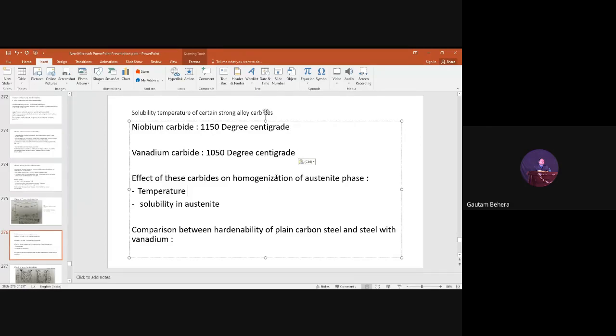Then the effect of this carbide on homogenization of austenite phase. So what we talked about the solubility here, that means, but in this case, what happened to the homogenization of austenite? Yes, homogenization of austenite will be slow, right? So temperature effect, if you look, this carbide will be still stable at high temperature. They will not become soluble. The second one is solubility in austenite. It is sluggish.